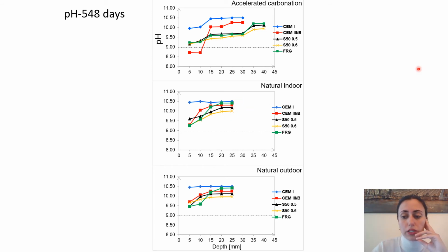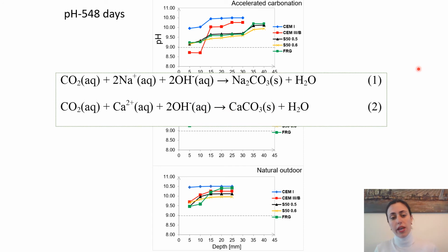of the concrete. So there are two main reactions which are happening when alkali activated concrete carbonates. First of all, the carbonation of the pore water with all alkalis that are inside together with CO2 molecules, where we have formation of the sodium bicarbonates or sodium carbonates. Then we have also formation of the calcium carbonates if there is, of course, a source of the calcium oxide in the matrix.